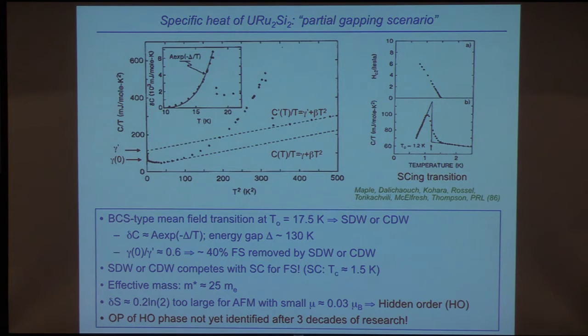In fact, Paul, I think you worked on a similar compound and inferred similar behavior. Do you remember that? Yeah, I think so. And then the effective mass is about 25 times the electron mass. Now it turns out that there's a large amount of entropy removed here, of about 0.2 log 2, and it's too large for such a small magnetic moment, and this is what gave rise to the terminology hidden order, and as I mentioned earlier, the order parameter of this phase has not yet been identified after 3 decades of research.